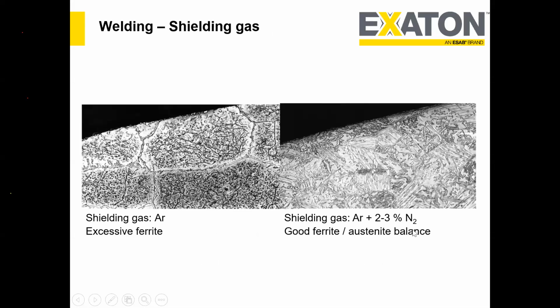So this is a microstructure. It shows that if you use a shielding gas of single argon, we get an excessive amount of ferrite. But if we add 2 to 3% nitrogen, we get a good balance of ferrite and austenite, because nitrogen is basically an austenite former, and it gives a quite good amount of austenite in the microstructure.